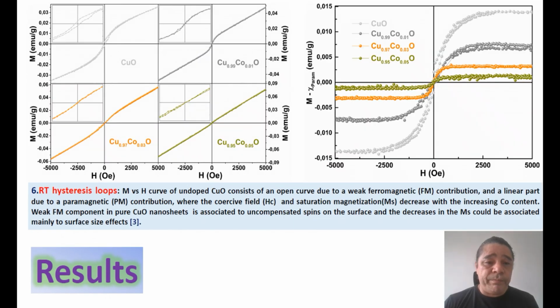Magnetic measurement. The undoped copper oxide sample exhibits a ferromagnetic contribution, along with a paramagnetic contribution, where the coercive field and saturation magnetization of the cobalt copper oxide samples decrease when the cobalt content increases. The ferromagnetic component in pure copper oxide nanosheets is associated to uncompensated spins on the surface, and the decrease in saturation magnetization in the cobalt samples could be associated primarily to surface size effects.